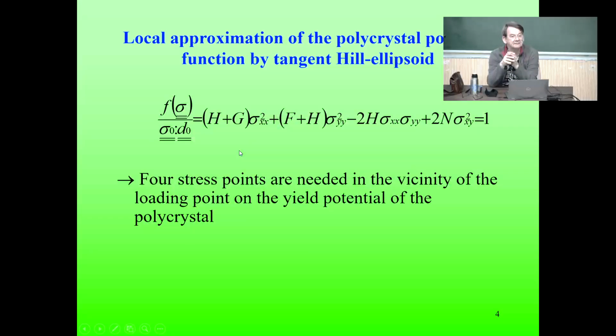To fit the polycrystal yield surface with the ellipsoid, we need 4 stress points in the vicinity of the loading point. Those 4 stress points will then produce 4 relations in which the unknowns are F, G, H and N. These 4 stress points are calculated with the polycrystal code near the loading point, and then this fitting is done. This requires a small program.